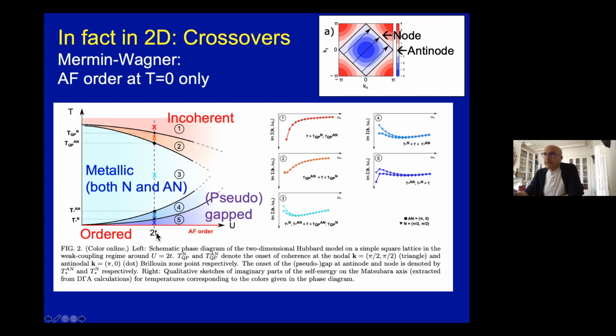And hence, there are really five different crossovers, five different regimes in this problem, plus of course the sixth one, which is the fully ordered T=0 ground state, antiferromagnetically ordered. So you see that simple as it is, this intermediate coupling regime in the two-dimensional case is particularly interesting. And of course, each of these regimes has a specific signature when you look at computationally accessible quantities like the self-energy as a function of Matsubara frequency.